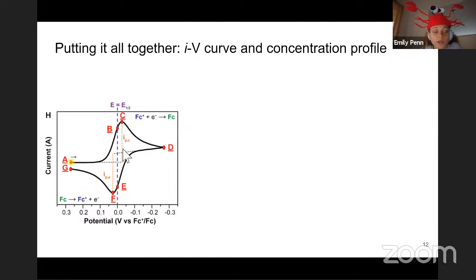So if we put all these together, we can look at what the current-potential function looks like for a CV experiment. There's a few different things which I'd like to point out on this plot. First, we have the two different peaks. We have the cathodic peak, which is at C, and then we also have the anodic peak. These peak heights are one thing that you might want to measure. We also have this E1/2, which is the half-wave potential, and that's going to be the redox potential for your reaction. Another factor that you might want to look at for CV is the distance between these two different peaks, the delta E between the anodic peak and the cathodic peak.